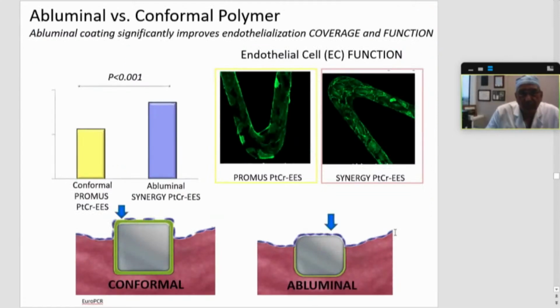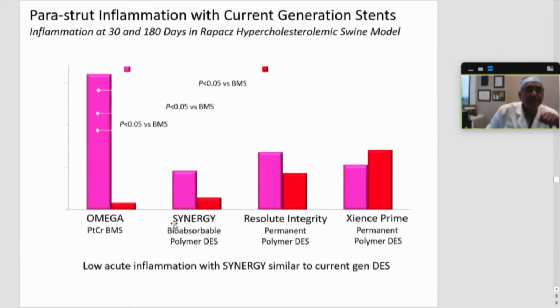So one can make an argument that if you have an abluminal polymer, which is only on the outside side, this allows for a very proper endothelial cell function as well as coverage. Unlike that, with the conformal, you actually have a lot of breakage on the endoluminal side because the endothelial cells cannot grow uniformly.